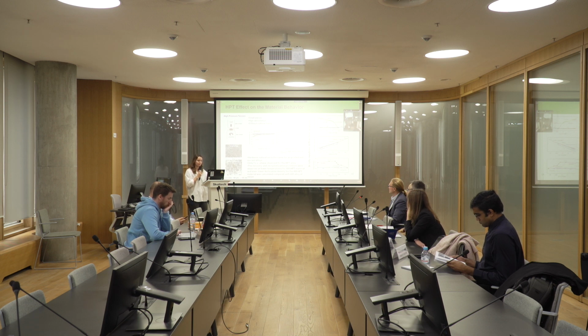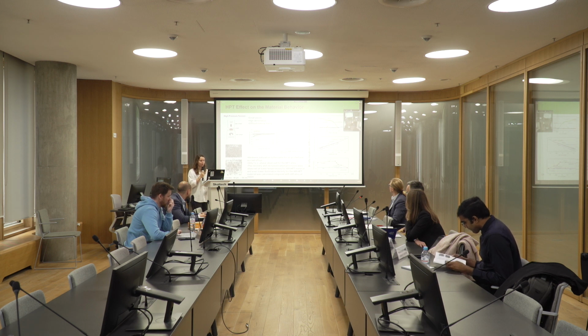But analysis of the further works demonstrates that it is not. In case of this 4-component system, I know that for the HPT materials of the 5-component system, there is the formation of a new phase. I'm not sure it's sigma phase, but they observed a kind of TRIP effect in this material, but only after the severe deformation process, like 14 turns of the 40 turns in case of the high pressure torsion. And in this case, our maximum is 8 turns.